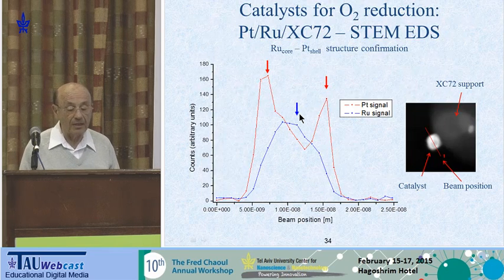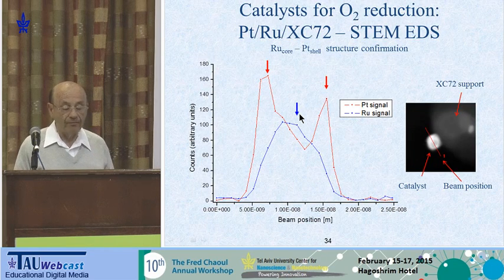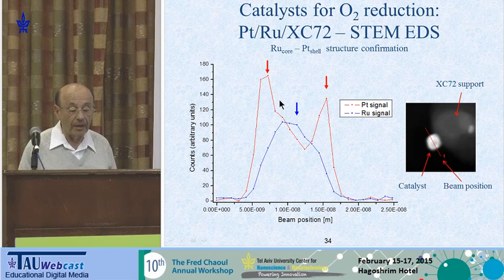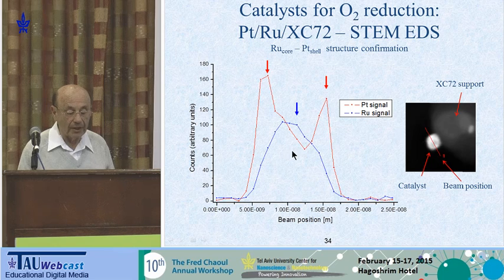So this is a very nice example and very nice STEM EDS micrograph, and this is the particle, and this is the line for the EDS, and what you see, the blue one is the ruthenium particle, and we deposit platinum on as a shell. As clearly you see that you have platinum outside and ruthenium inside, that's very clear evidence that we are able to really get what we like, a platinum shell on ruthenium core.